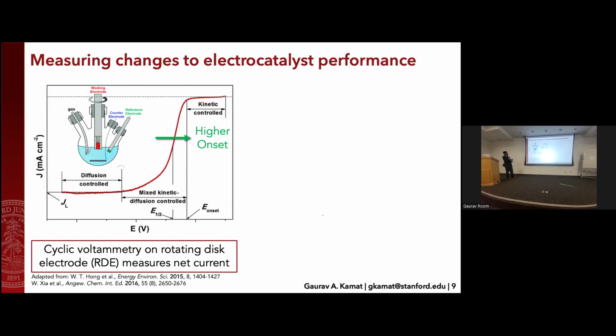And this shape here is a cyclic voltammogram, which is taken by adjusting the potential and recording the current density that your catalyst is able to achieve. And for the oxygen reduction reaction specifically, as this moves further to the right, closer to 1.23 volts versus RHE, I should say, that's the onset or the equilibrium potential. So as it moves further to the right, you have a better catalyst that onsets earlier.